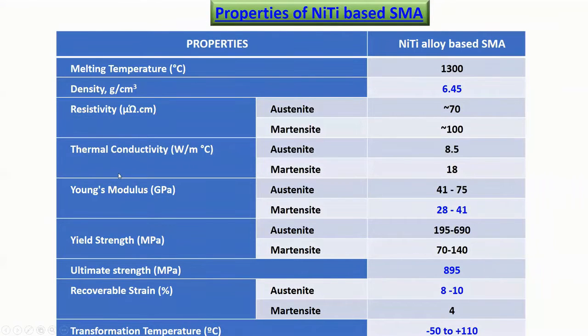Now that we know that nickel titanium is giving us the best of the properties, we'd like to have a look at what these properties are. As I have said, the two phases of importance here are austenite and martensite, and the different properties are shown for both these phases. These blue ones highlight the properties of interest if you're talking about mechanical applications. And we see that the Young's modulus of the martensite phase is the lowest, which is very similar to human bone. For human bone, it is around 10 to 20 GPa.